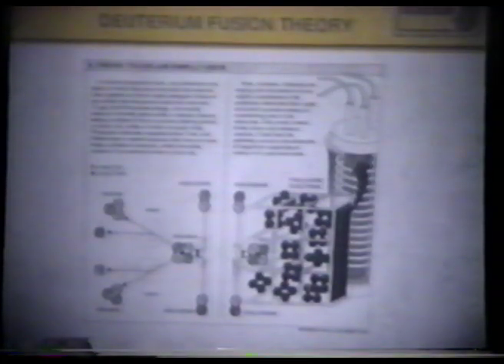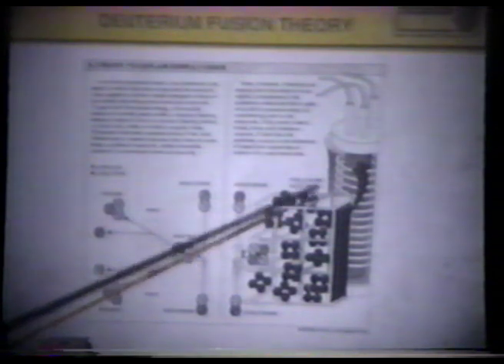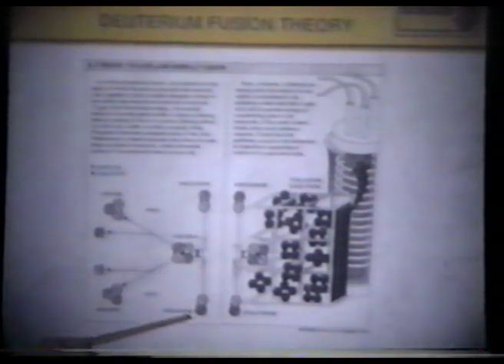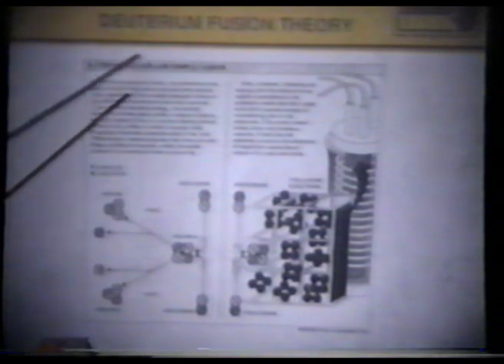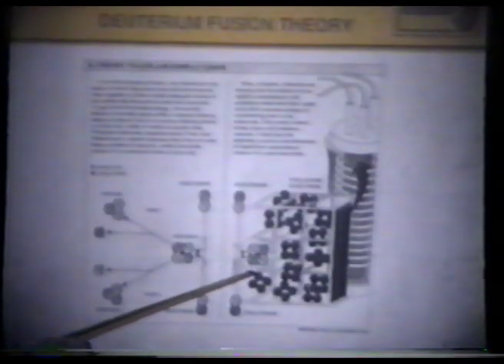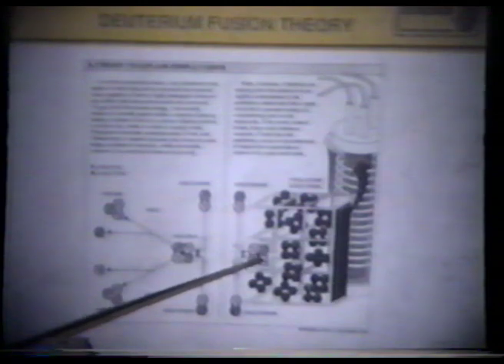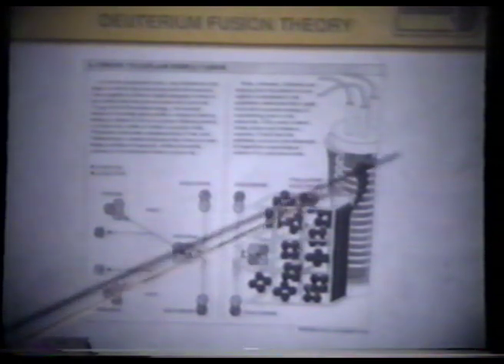Well, early on in the story about cold fusion, this appeared in the Los Angeles Times, probably April, I forget, but they were already advancing the theory at that time that the lattice under these pressures may change the reaction pathway considerably. Instead of the normal hot fusion pathway, where it goes through a helium-4 intermediate, but has such tremendous energy that helium-4 is not stable, and so it splits either into helium-3 or tritium. But inside the metal lattice, if that's where it's taking place, perhaps this excess energy of this excited helium-4 can transfer its energy to the metal lattice and stabilize itself and appear as helium-4 as a product. With this condition of the metal lattice in the electrode.